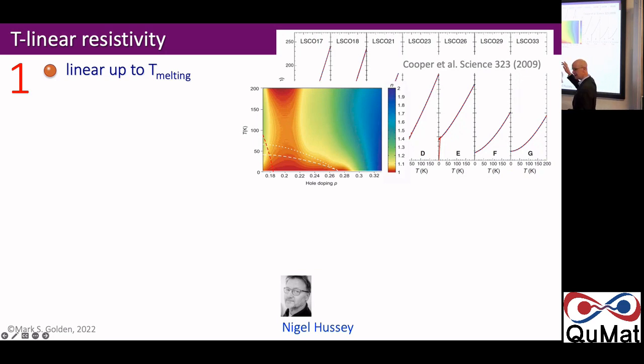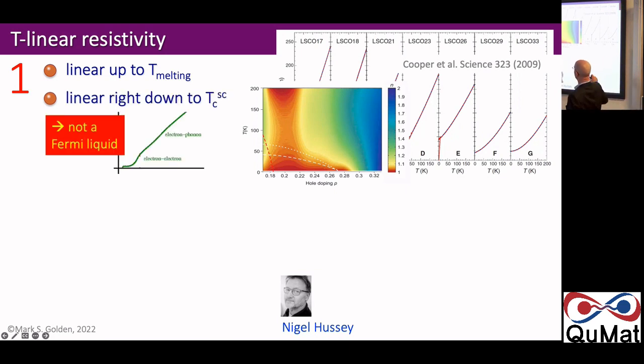And it's at low temperature getting linear resistivity that's theoretically really difficult to explain, because there it's all the electron-electron interaction that is driving the lifetime of the electrons. And so you should be getting this. These things have a Fermi surface. There should be this T-squared thing popping up if they're regular metals. So linear resistivity right down to the superconducting transition temperature means these things are really not a Fermi liquid. You have to put that aside. And then the experimentalists are challenged: how do we even talk about our data, as all of the words and concepts we use are the ones belonging to this quasi-particle lifetime? So the theoreticians are then challenged to give us a new language in which to describe this, other than by just saying what it isn't.